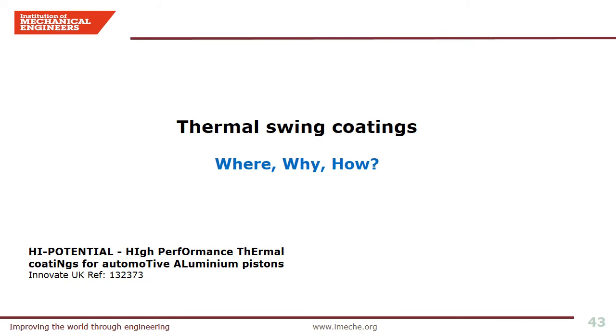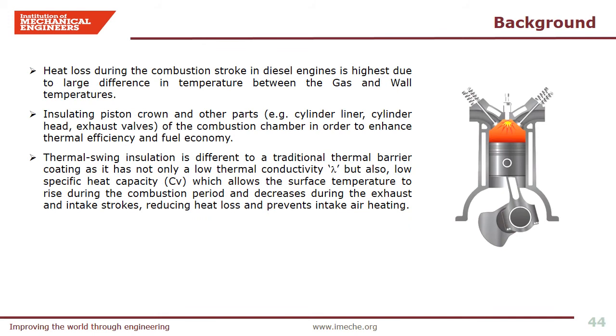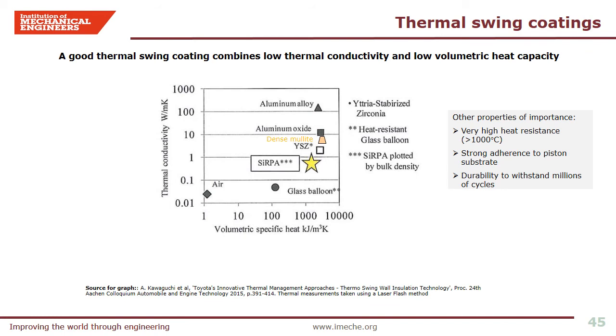Another interesting area for the PEO technology is the thermal swing effect and how it may help improve vehicle fuel efficiency. One recent project we investigated was High Potential, funded by Innovate UK. Heat loss during the combustion stroke in a diesel engine is highest due to the large temperature difference between gas and wall temperatures. Insulating the piston crown and other parts of the combustion chamber using PEO helps enhance thermal efficiency and fuel economy. Thermal swing insulation differs from a traditional thermal barrier coating in that it has not only low thermal conductivity but also low specific heat capacity, which allows the surface temperature to rise during the combustion period and decrease during the exhaust and intake strokes, thereby reducing heat loss and preventing intake air heating.